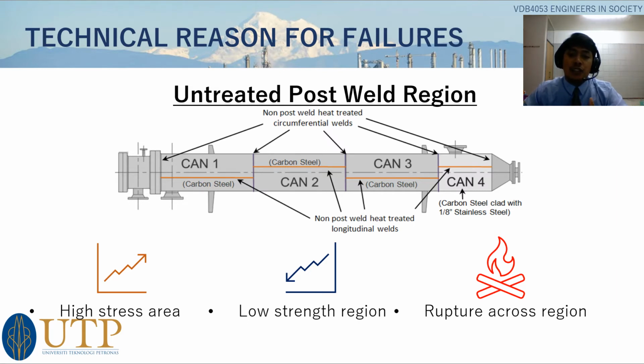Due to the untreated post-weld region, there was a higher stress area and a lower strength region that made hydrogen attack prone to happen. This caused more hydrogen attack with a bigger effect on the carbon steel. This technical reasoning was supported by the CSB findings, as the rupture occurred across the untreated post-weld area.